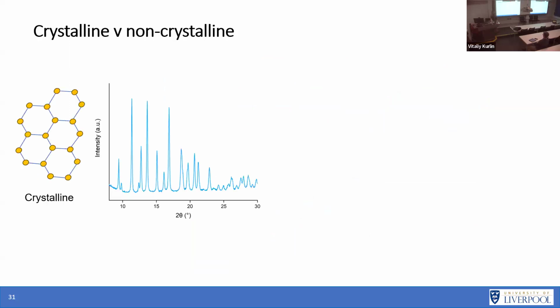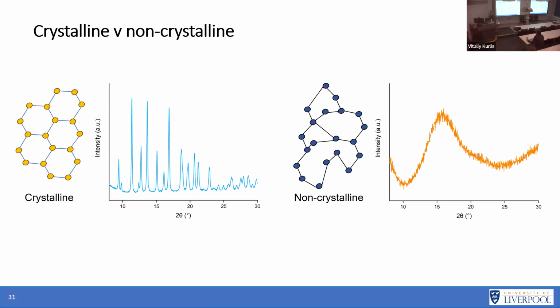So when we talk about crystalline and non-crystalline frameworks, what do we actually mean? In this crystalline framework that we spoke about before, if we did a powder diffraction pattern, it would look something like this, right? We'd have this nice crystalline pattern with lots of peaks in it. When we look at these non-crystalline frameworks, we're talking about very disordered systems, and we typically get a powder diffraction pattern that looks like that. It's fine because it tells you that you've made something non-crystalline, but you can't really get very much information after that. So PXRD is certainly helpful as a fingerprint, but I wouldn't say it's the be-all and end-all for looking at these structures.